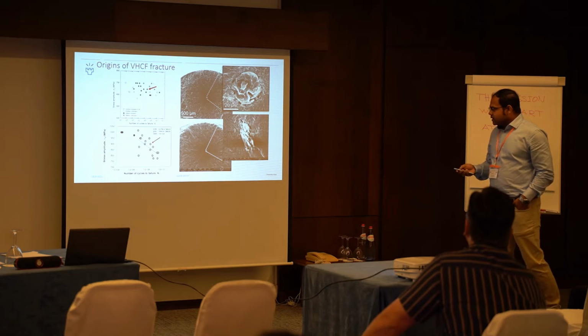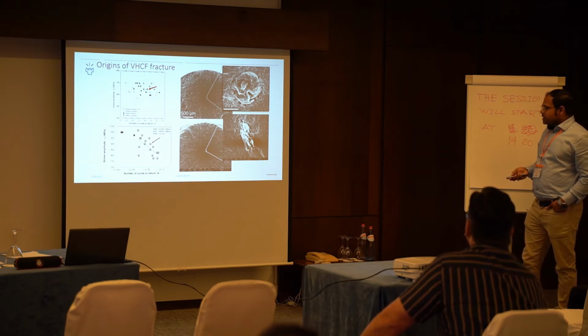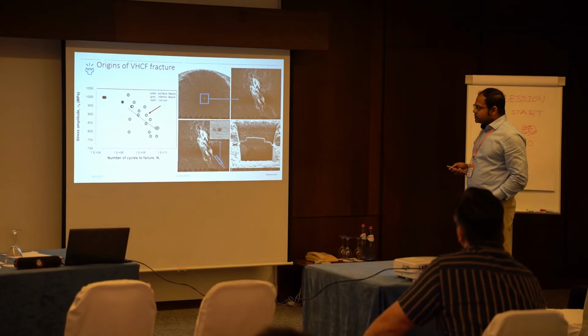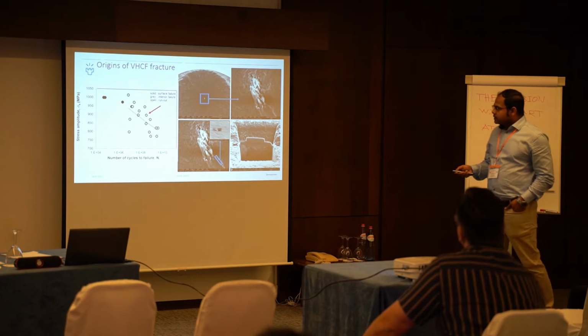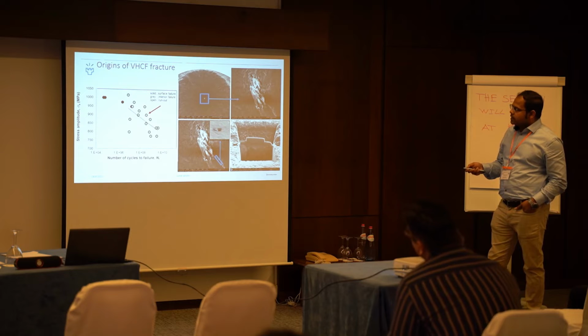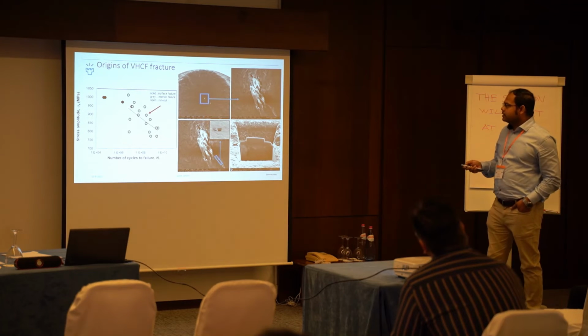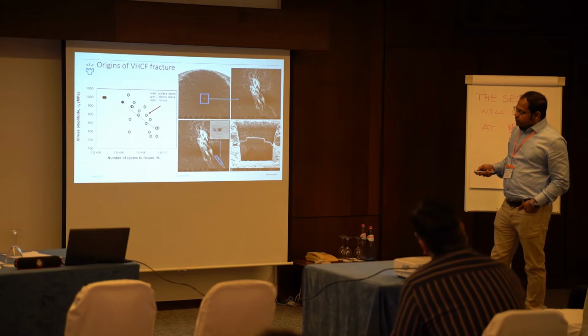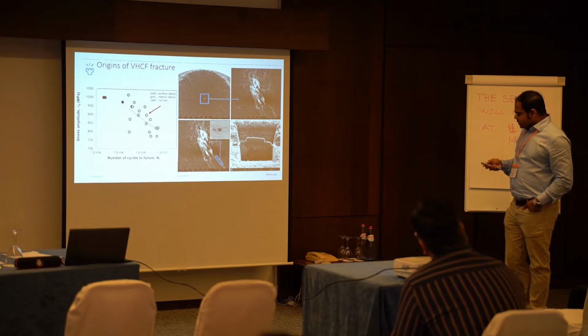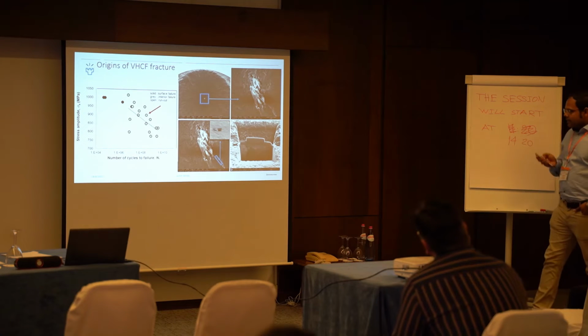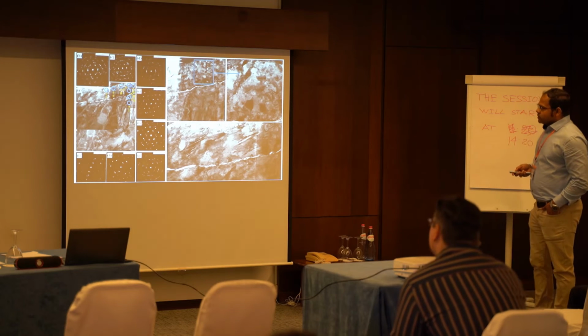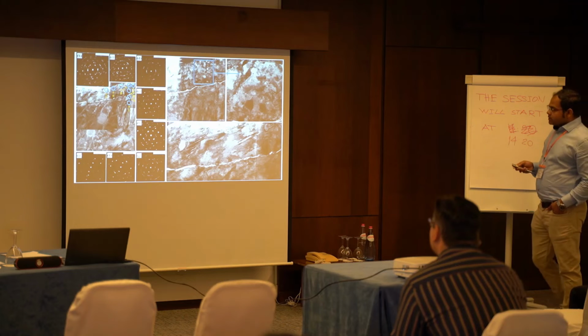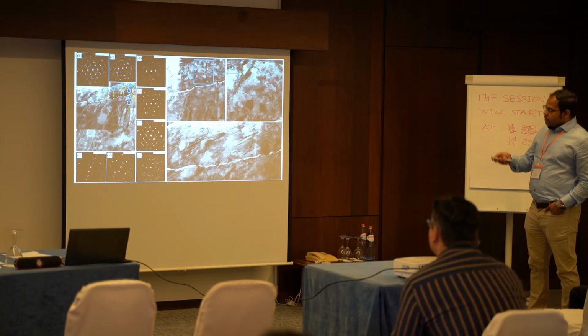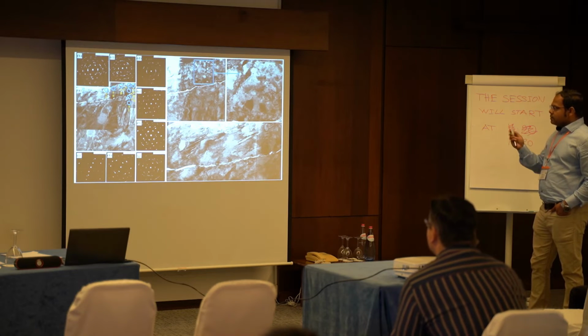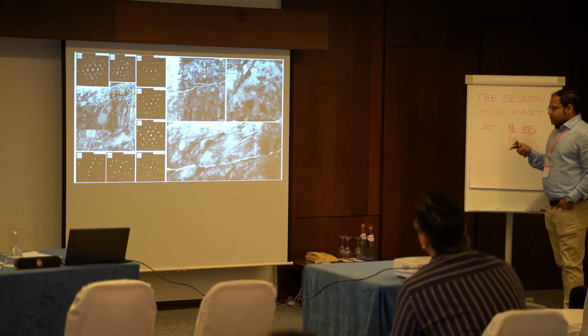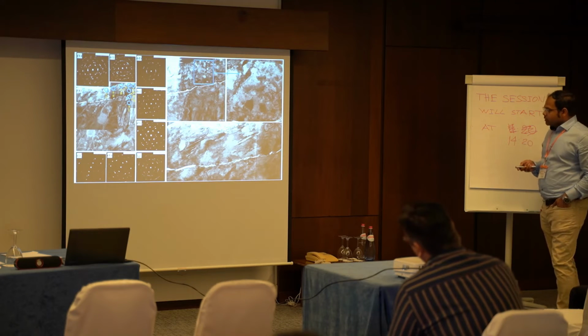In order to further investigate the micromechanism associated with this failure, we investigated this certain condition. We selected this particular specimen, which failed after 10^8 cycles, and prepared a FIB specimen lifted out adjacent to this failure region. When you see this specimen under TEM, we clearly see the fine granular structure formation, which we measured based on selected area diffraction, and also along different axes. We assumed the diameter of this fine granular area is around 1-2 micrometers around the inclusion.